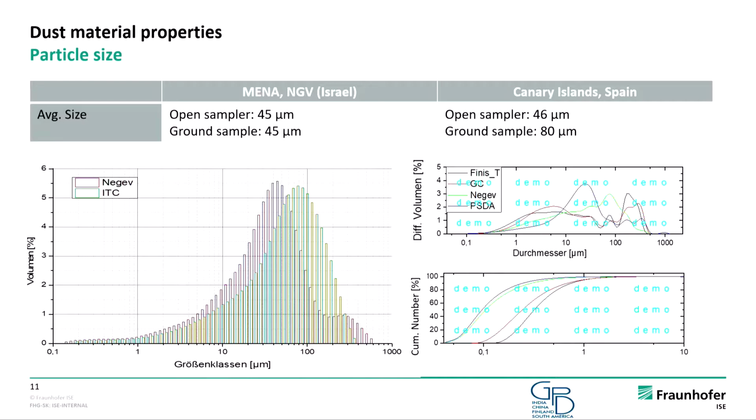Yes, and here we can see the particle sizes. Sorry for the demo pictures. We have been on the way for 2 weeks, and my origin license has only 24 hours, so it ran out. I have to update that again as soon as I'm home. If you look into the particle sizes, you can do it with laser diffraction, which we did here, only on larger amounts. Here you can see the difference of the two locations, Negev and Gran Canaria dust. Here's the 80, and here's approximately the 45, so you have really determined peaks.